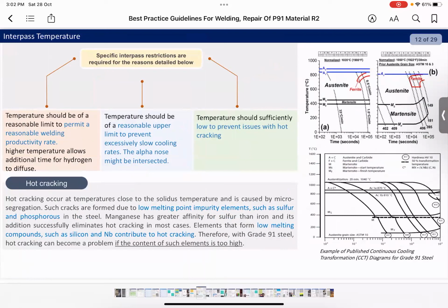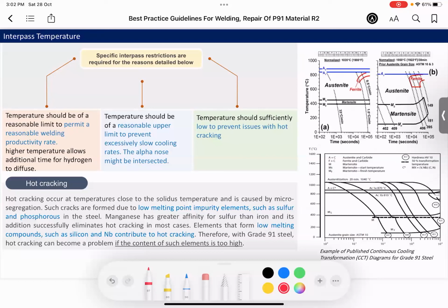So slow cooling here, as you see here, if you have slow cooling, it might intersect the alpha nose here, and you will not have a martensitic structure. So it should be high enough to have a proper cooling rate of the weld. The interpass temperature also should be sufficiently low to prevent issues with hot cracking.